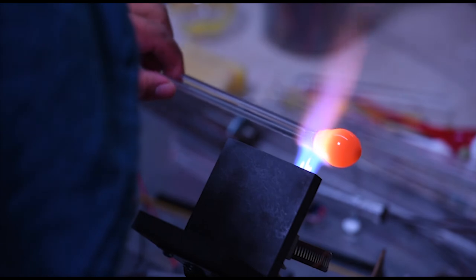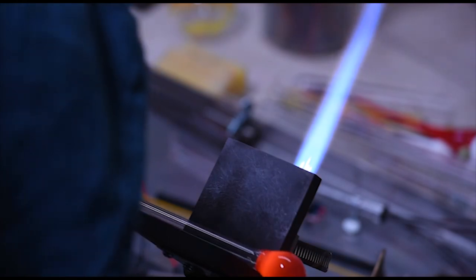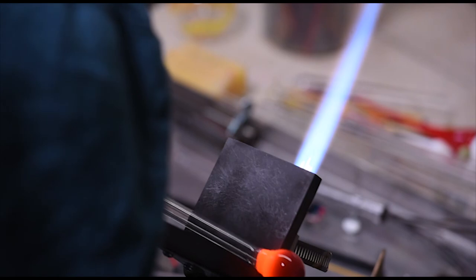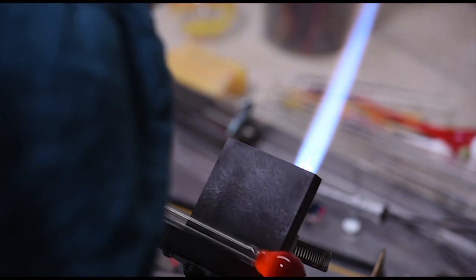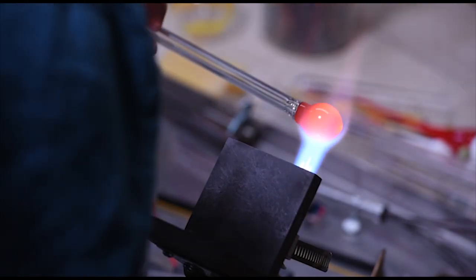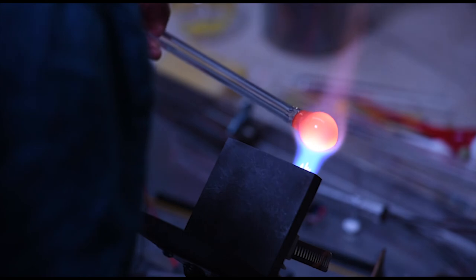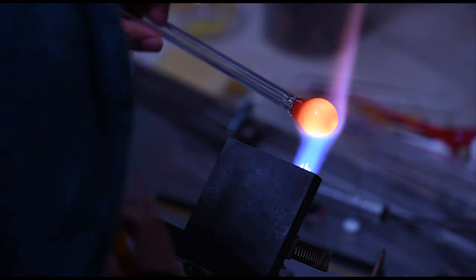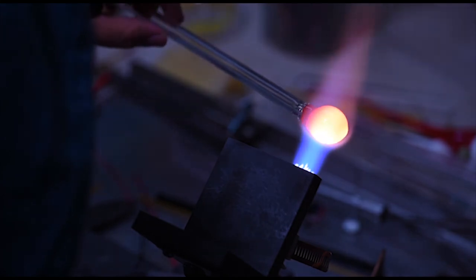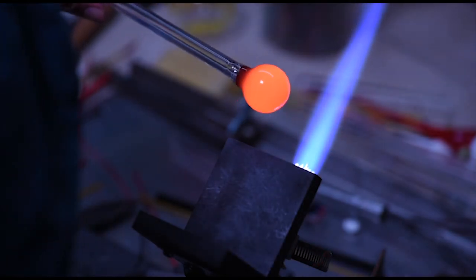There's a lot of repetitiveness in glass — heat, puff it out a bit, and reheat — but that's how you learn. Using the marver here a little bit: there was a tiny hole where the black met the clear where I first started coiling. If you have a hole in there and you're trying to blow this glass out, the air just comes out the hole and the glass never bulbs out like you want. Make sure from the start that you get it on there nice and solid with no holes. Now that everything's airtight, give this another heat and blow it out into a nice sphere with thick walls.